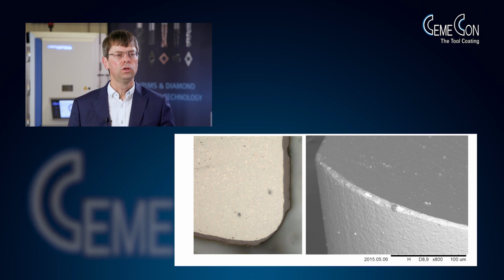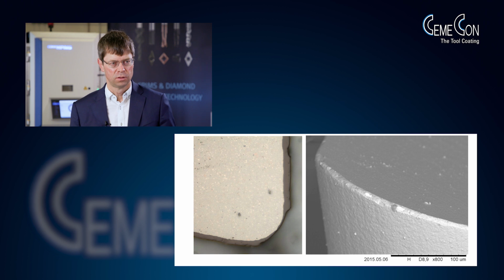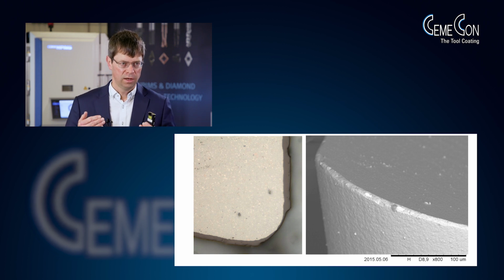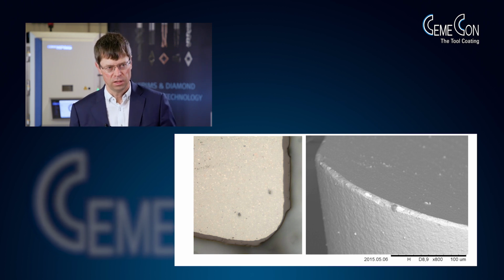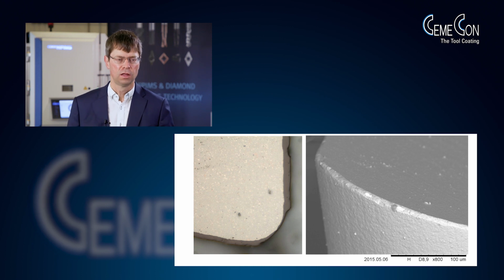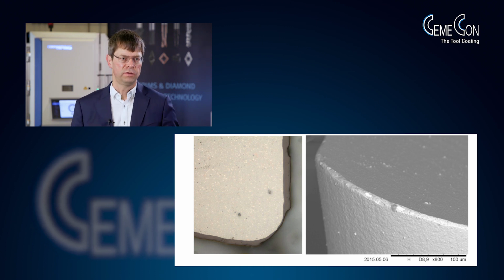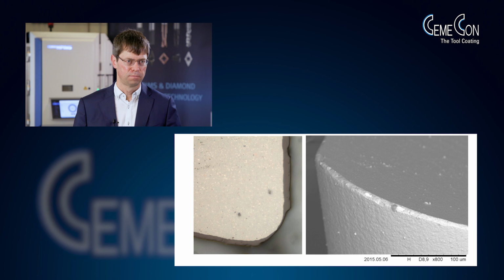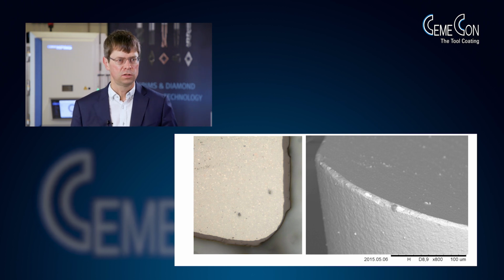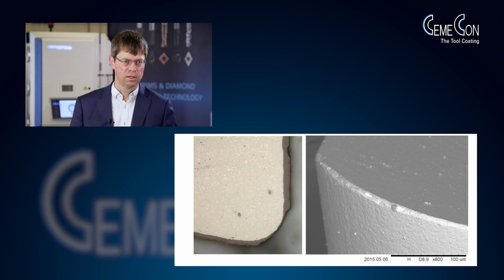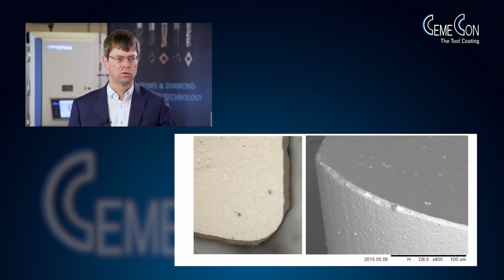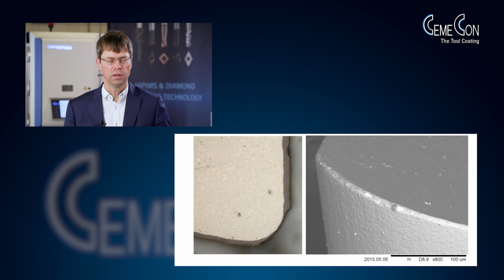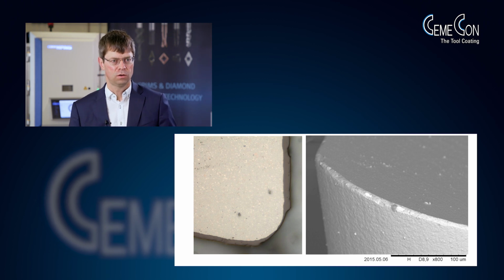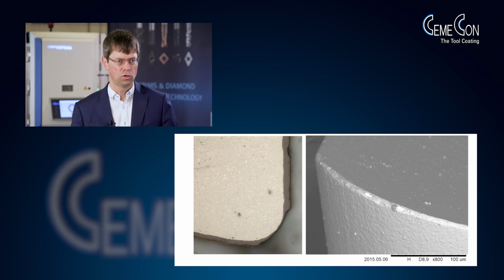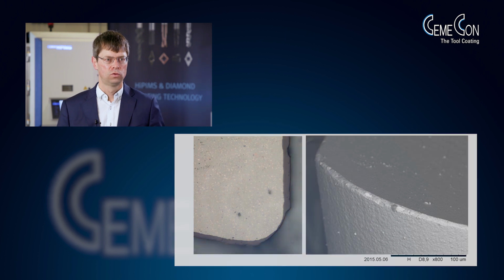Well, from your tool point of view, you grind a nice surface, you prepare your cutting edge, you do a honing process, and then you give it to a coater, and when you get it back, you see this. Spallation of the coating, peeling, or the cutting edge is no longer coated fully. You see at some spots even the carbide. Obviously, the intrinsic stresses in the coating were not fitting to the geometry. Well, how to avoid this?